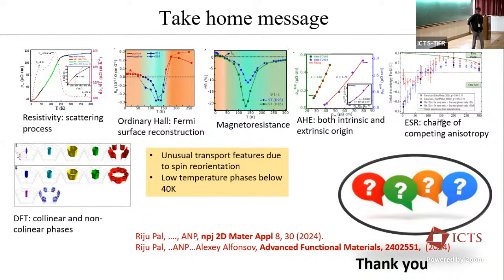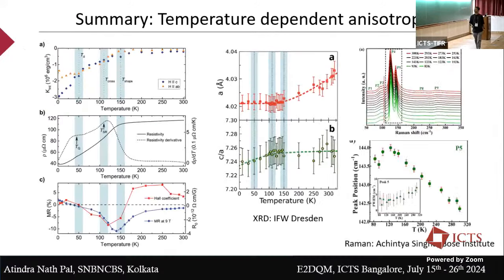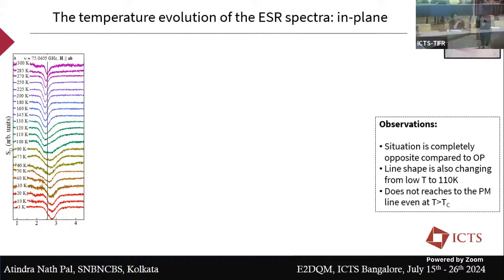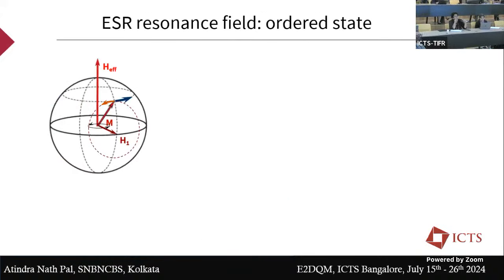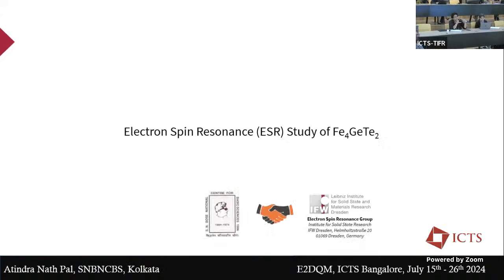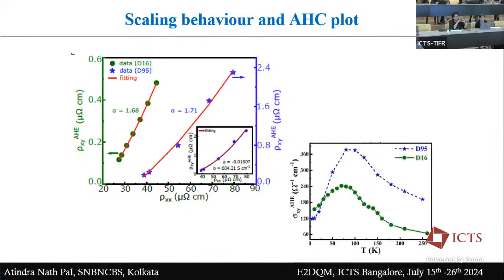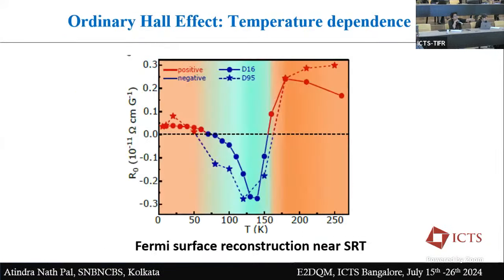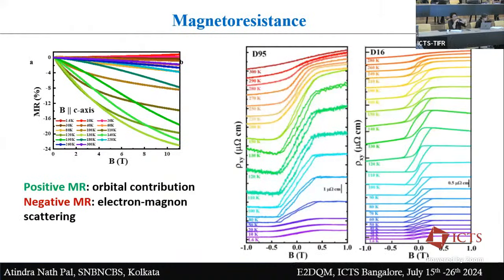Question. If you go back, there was this anomalous Hall data. The hysteresis is not a conventional anomalous Hall, but there is much more to it. Do they correspond to some spin textures? If you look at something like 120 Kelvin and below, that is much more. Magnetoresistance also increases very much near the spin reorientation, and also hysteresis is maximum there.